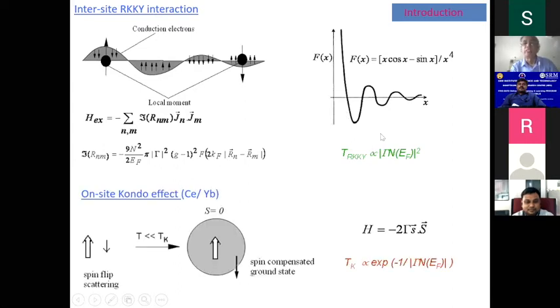Now that is another interaction. RKKY promotes magnetic ordering. There is another interaction, the Kondo interaction, which is trying to suppress magnetism. A local moment at this site can be antiferromagnetically coupled with the conduction electrons. Here it is a ferromagnetic interaction; here it can have an antiferromagnetic interaction. It's called the Kondo interaction, and it is trying to suppress magnetism. There is a competition between the two interactions. One interaction is trying to promote ordering because of the oscillatory nature of the conduction electron polarization. The other is trying to suppress magnetism because of the tendency of the on-site interaction to promote non-magnetism. This interaction goes exponentially with the same exchange interaction strength. One goes like a square, the other exponentially. There is a competition between the on-site Kondo interaction, with different Kondo temperature.